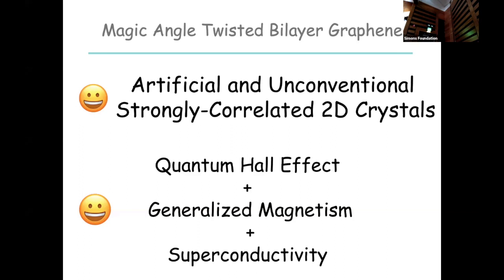But I was proposing at the end that this multi-branch set of collective modes that appear in calculations we've done recently are a candidate for being responsible for the linear T resistivity. And it seems quite plausible to expect that whatever is responsible for the linear T resistivity could be responsible for the superconductivity. And time for me to get off the stage.